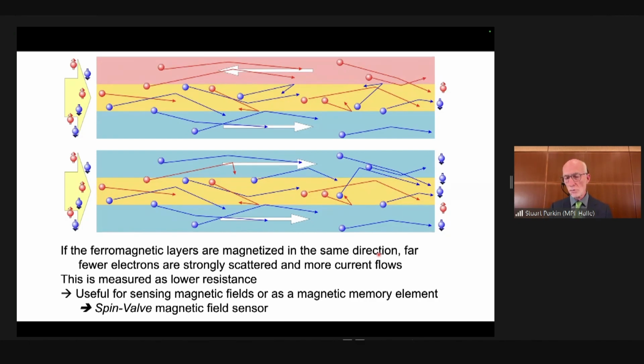And it turns out when we properly spin engineer this device for maximum sensitivity, we demonstrated that this type of spin valve sensing device can sense magnetic fields at room temperature 1,000 times more sensitively than any other device at room temperature. So this enabled us to introduce this sensing device into a magnetic disk drive and detect magnetic regions, the magnetic bits, 1,000 times smaller than was previously possible.